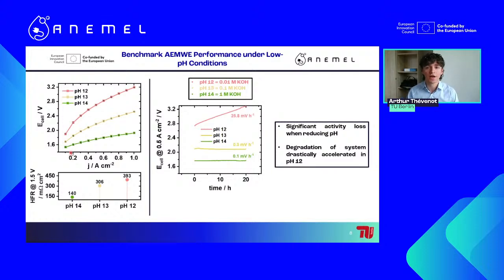So as we see here, in the pH 14 electrolyte, we have very satisfying results that are even industry relevant, as we have 1 amp per square centimeter below 2 volts, which is, I would say, the minimum requirement to go to the industry. But then, if you go to pH 13, so decreasing to 0.1 M, you have a drastic loss of performance actually already. And then even going lower to pH 12, you have an intolerable performance drop. You cannot do anything with this. You can just discard it.